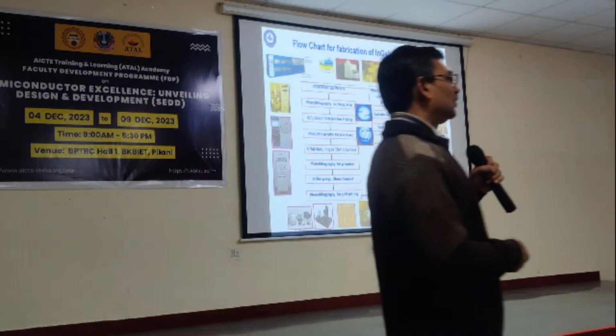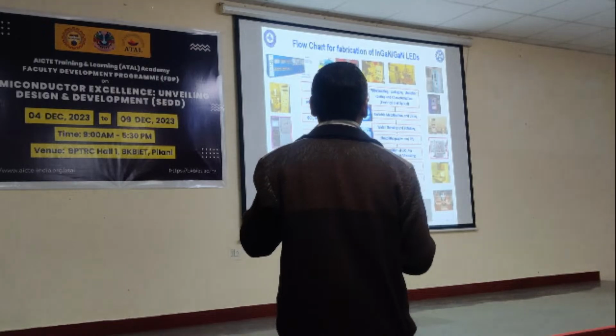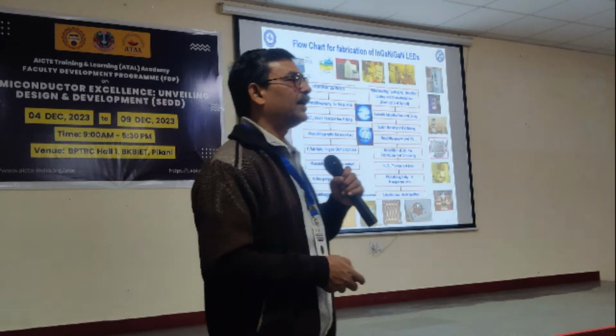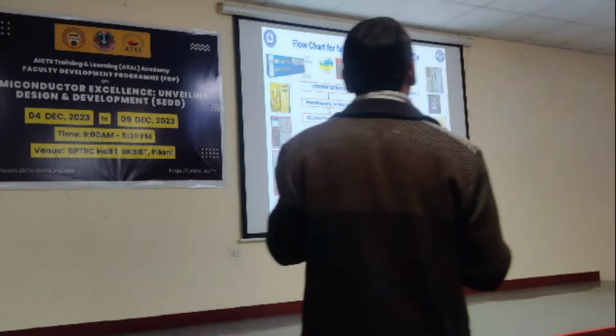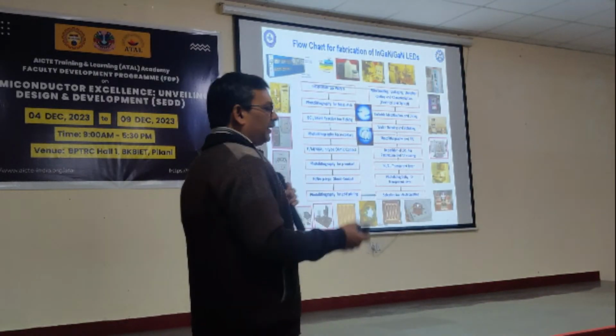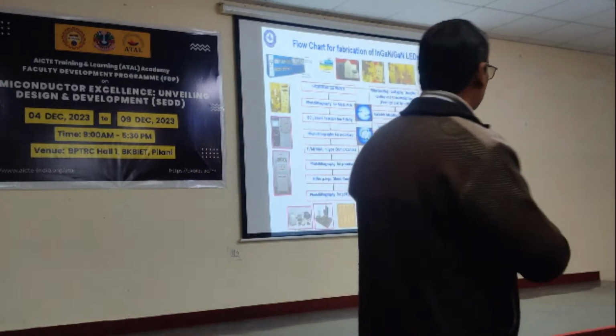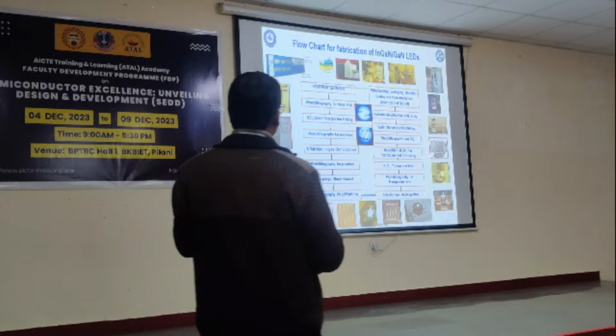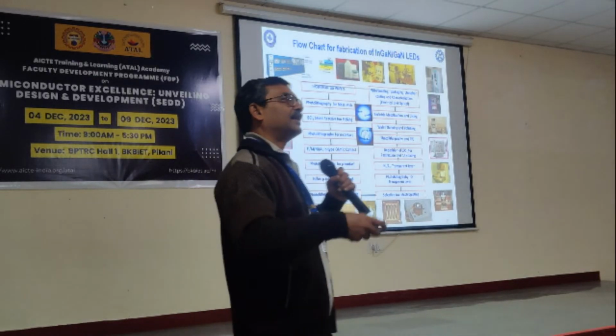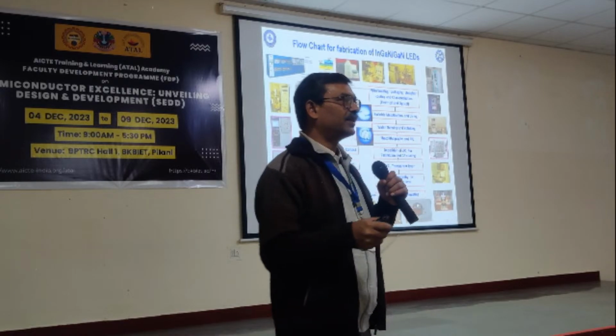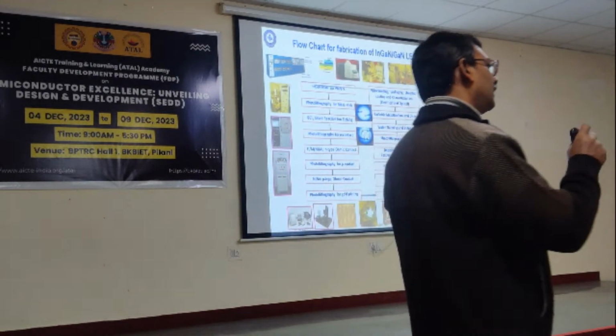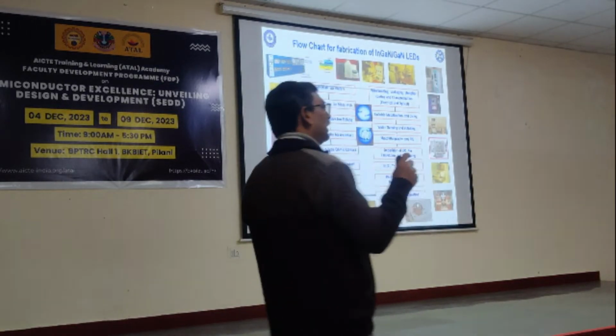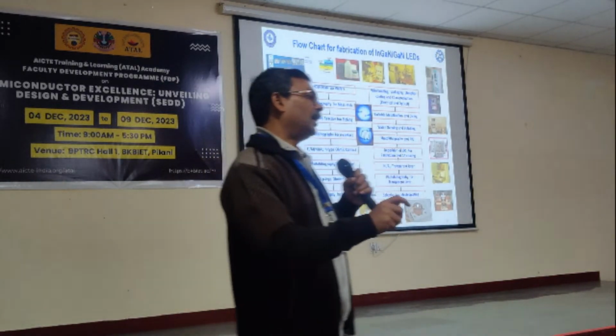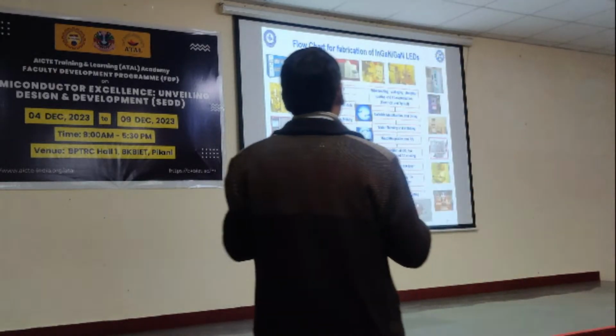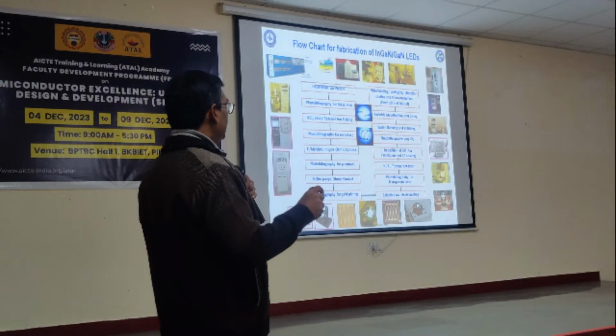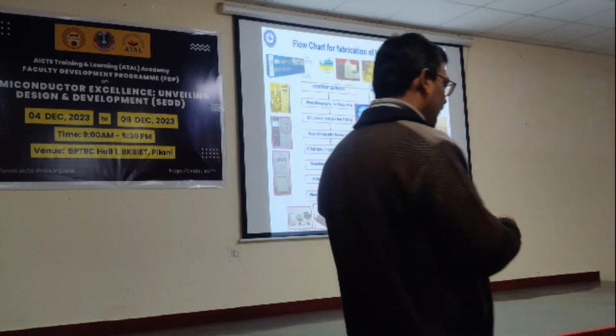After packaging, we go for characterization, to see what the emission is, whether we are getting it in terms of our design or not. And for white light, we have to coat yellow phosphor on top of the blue light. So we go for the yellow phosphor coating. That is another optimization. What is the phosphor concentration? What should be the thickness of the yellow phosphor? We have to mix the yellow phosphor with some elastic polymer material, and decide what the thickness should be. All those things we have to optimize so that we can get exact white light.